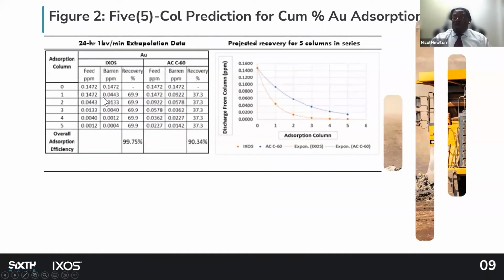Now with that, we did some extrapolation using a number of tanks, and we realized that if we put in 5 tanks, we're going to have close to about 99.75% recovery for gold, compared to activated carbon, which will be 90%. Now, with that in mind, we realized that would be a good thing to run on the field. We reached out to the client, and client was actually excited about this and wanted us to come to the field to run this test work.